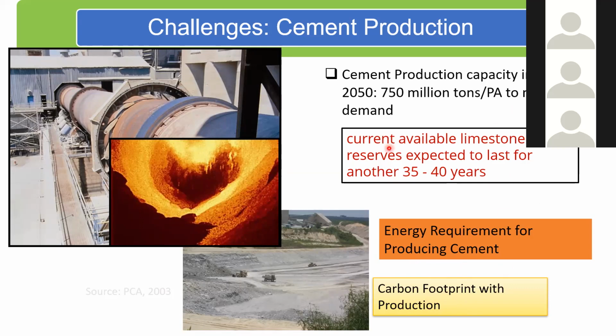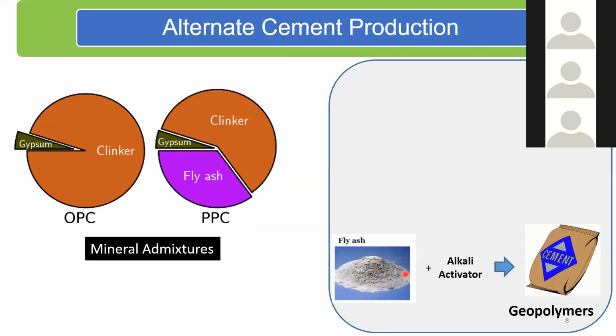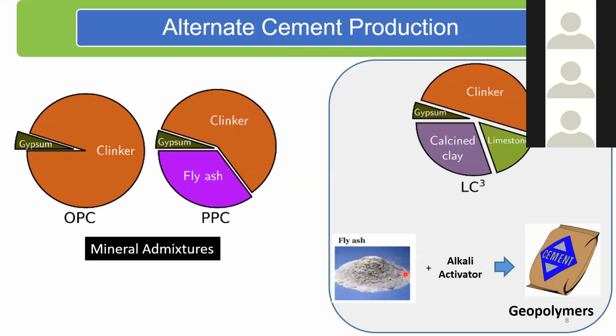So there's a lot of material technology development that is happening here, where we're looking for alternate cements, where we're looking at reducing the clinker factor in cements. We're looking at alternate binder systems. All of that is happening in parallel while we are working on trying to make our concrete more performance oriented. So just to give you a brief snapshot of what is happening, this is our conventional OPC, where we use clinker and gypsum. We grind them together. Typically, gypsum is about 5%.